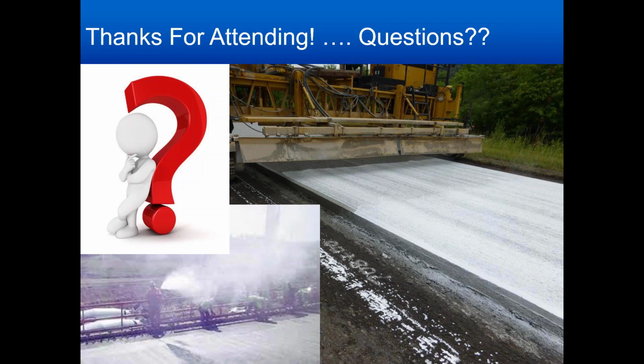There really isn't a risk of putting it on too soon. The bigger risk becomes trying to finish any of that material into the surface because it is 90 percent water. So they are called finishing aids. Another term, I don't really care for that term, but it does aid the finisher, but they're not meant to be finished into the concrete because of the amount of water that makes up that evaporation retardant. They're meant to lay there on top of the surface and then surface dry.